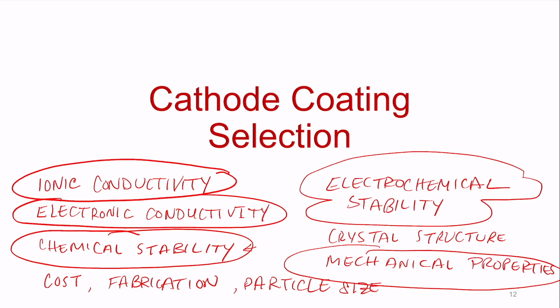If one has to rank, what are the big ticket items you should be concerned about when you're trying to screen for materials? These are the properties. Because if your material is not as stiff, if the elastic modulus is not as high, there's potential that it won't be able to suppress lithium filament growth, right? The lithium is going to grow and push your material straight out, grow past. Electrochemical stability, the induction of SEI and CEI, chemical stability, oxidative and reductive potentials.